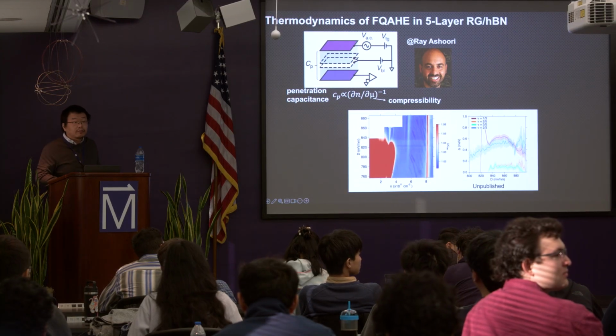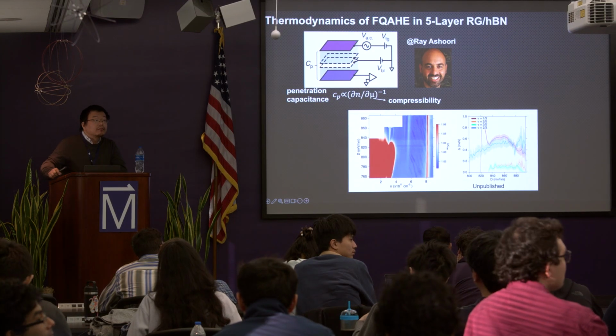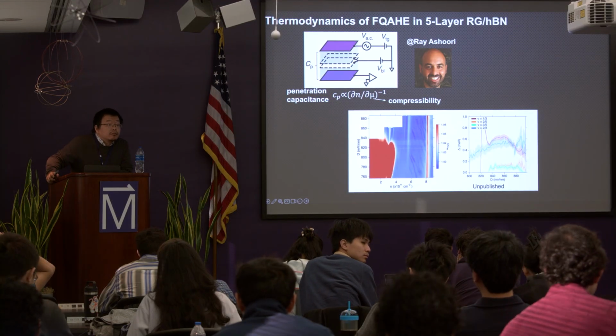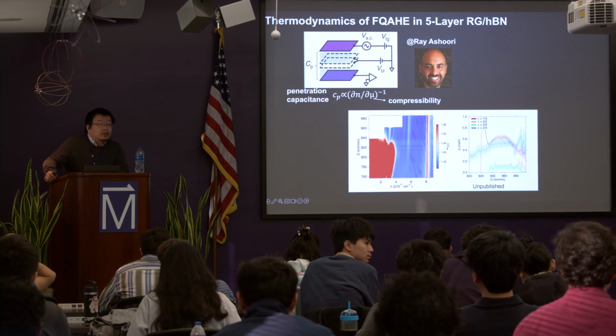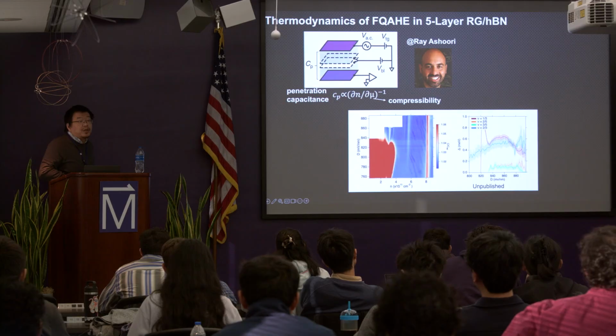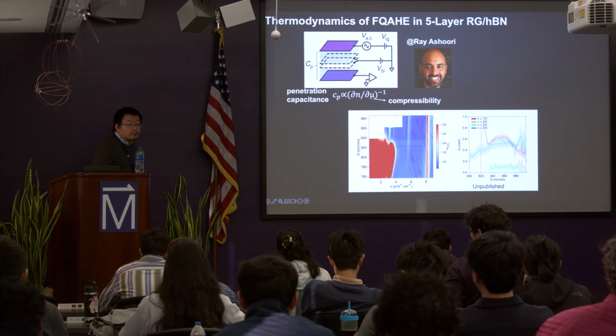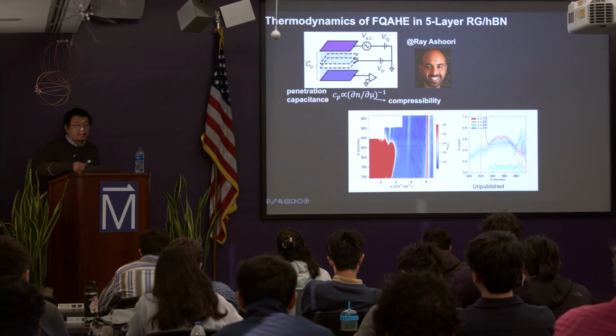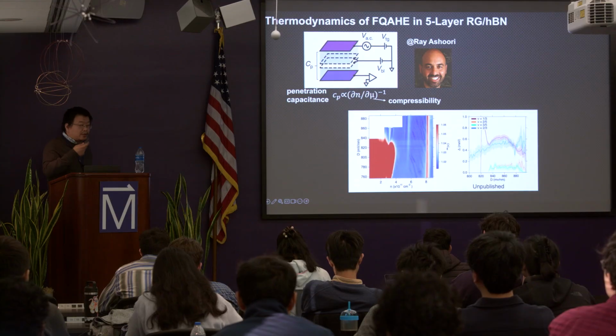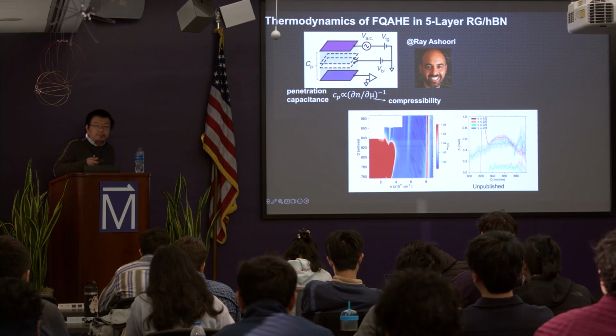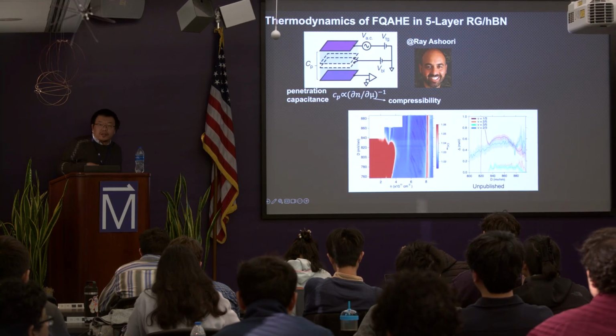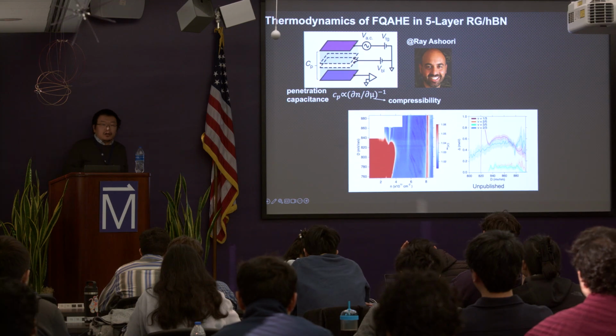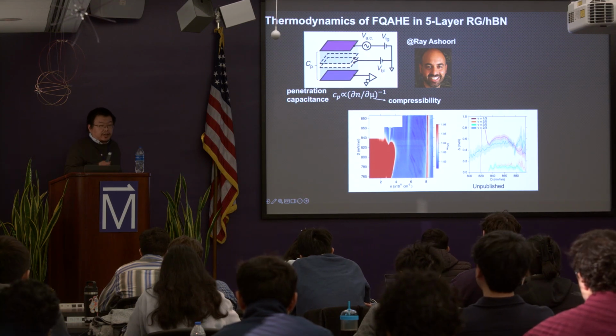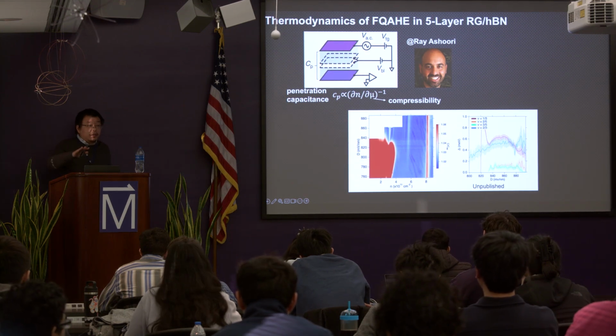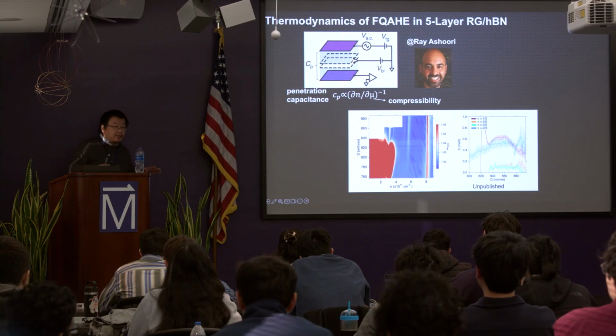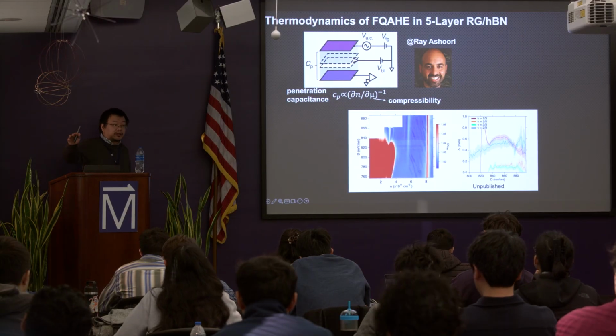It's about 200 millikelvin. So for that one, it's more or less like, I won't say experimental artifacts, but you have your electron temperature that is separate from your lattice temperature. So even if you do temperature dependence, it doesn't really mean anything. Your electron temperature saturates.